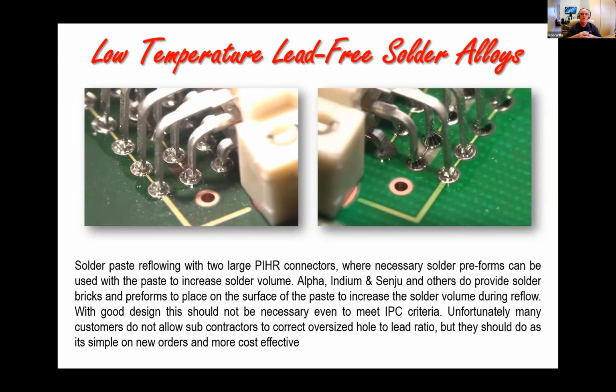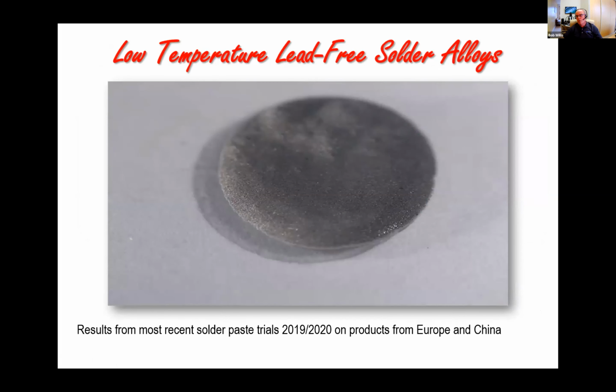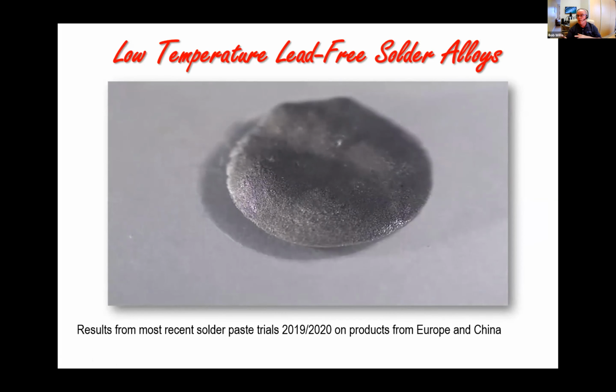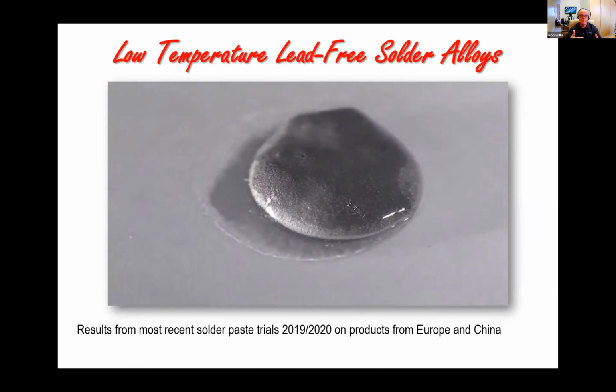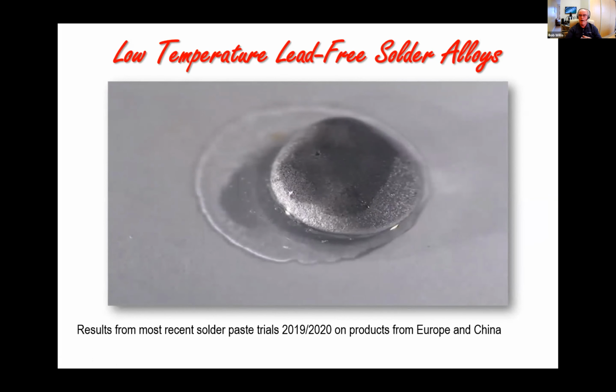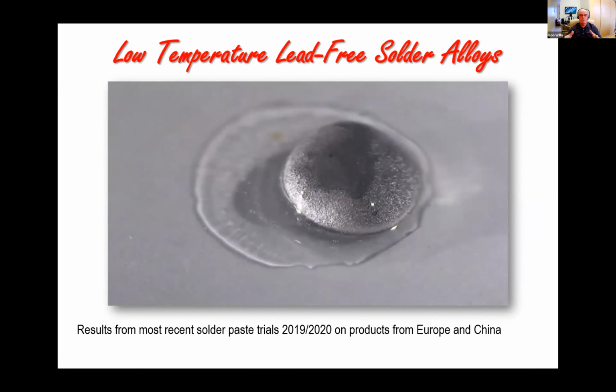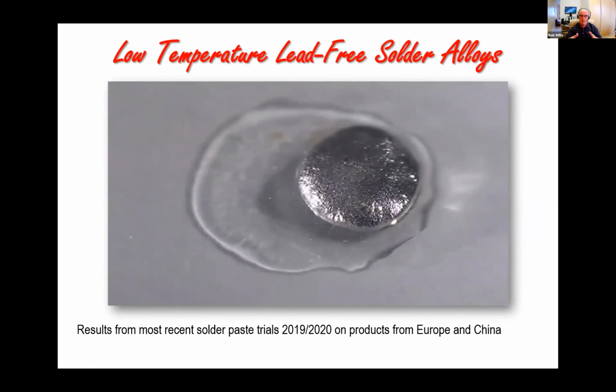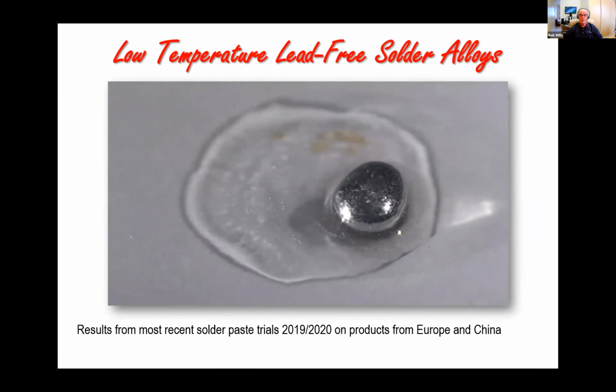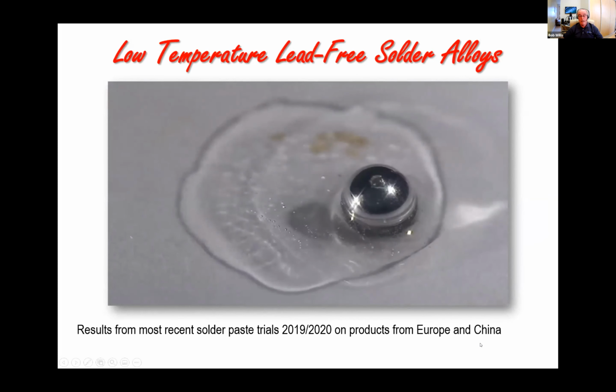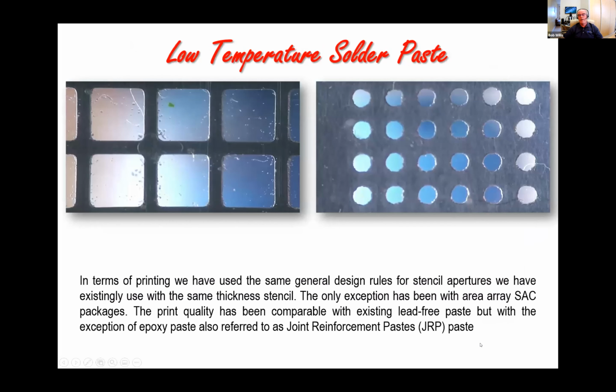And there is a benefit on the financial cost of the component, and it's fairly easy to achieve IPC standards with these materials, because it's the same basic volume of material that we're applying to the printed circuit board. When we move on to more recent trials in 2019, 2020, I was looking at materials both from Europe and also from China. And again, this is me looking at the material, its reflow characteristic, its slump characteristic. And again, pretty similar to any of the SAC materials you may be using today. So the actual materials being manufactured are quite stable and provide good printing characteristics as well as reflow characteristics.